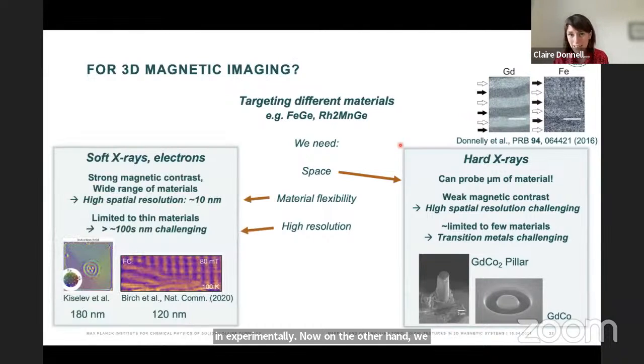Now, on the other hand, with soft X-rays and with electron microscopy, we have no problem in terms of the magnetic contrast. We have access to different absorption edges, so we can get much stronger magnetic contrast. And we also have very high spatial resolution. However, the challenge here is that we are typically limited to thinner samples because the penetration depth of these probes is not quite as strong.